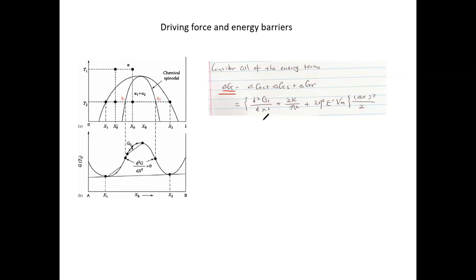Now in the first set of analysis, only focus on this first term, because when delta X is very small, the contribution of these two terms is very small. If we want to see whether the transformation can start or not from the thermodynamics, we do not have to take into account these two terms. But as the transformation proceeds, as the contrast of the composition gets larger and larger in the two regions, eventually the interface begins to play a role, and the lattice mismatch also plays a role. Comparing the terms, this one is going to be larger than this one, and this one larger than this one. Because they roughly have the same crystal structure, but just slightly different lattice spacing, the elastic energy contributes the least, and then the interfacial energy contributes next to that. This one may play an important role towards the end, but the major contribution is from the bulk free energy.